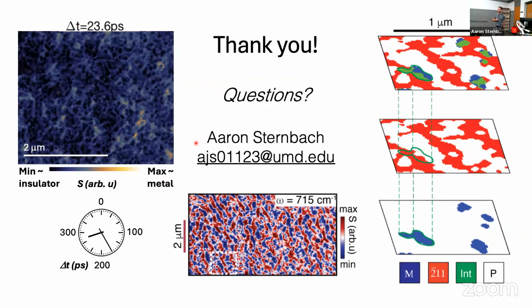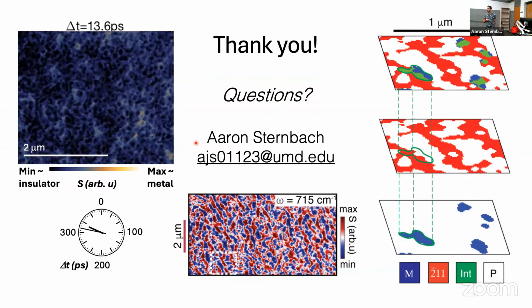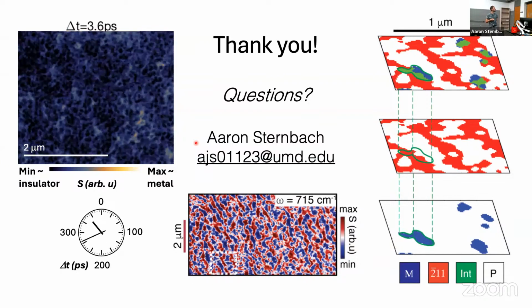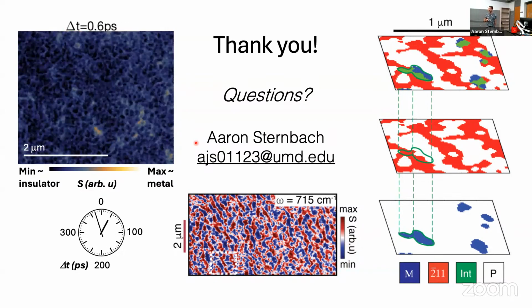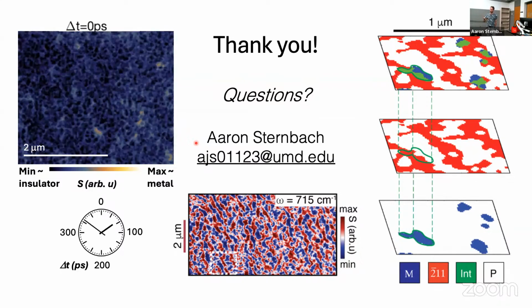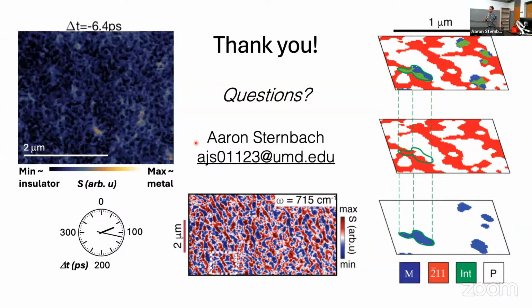Yeah. So what's the RMS roughness in some of these films, and also for the vanadium oxide, which you showed a lot of? What was the deposition method? Oh, okay. The deposition method, I have to remind myself because we studied various versions of this. But these are films on R-cut sapphire. The average thickness is around 100 nanometers, and then we have a granular pattern that we can see on the surface, which is about 10 nanometer roughness. So it's pretty rough.